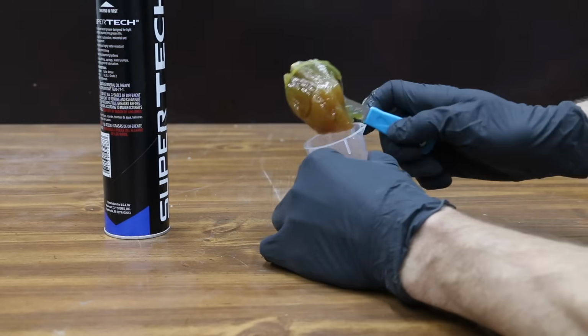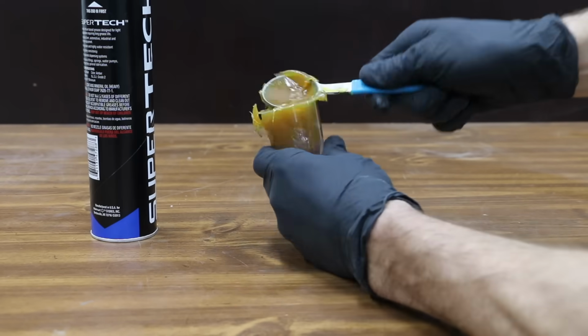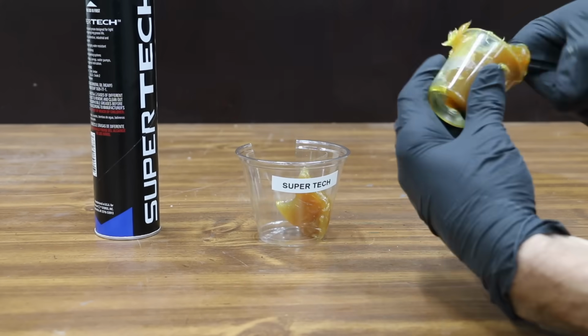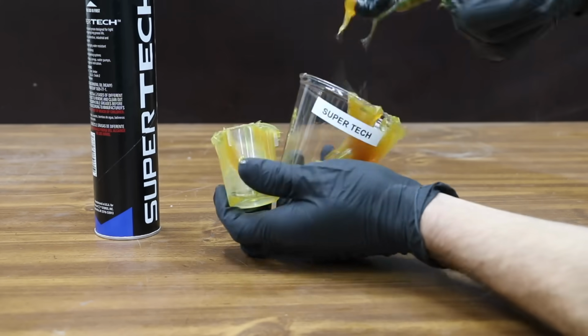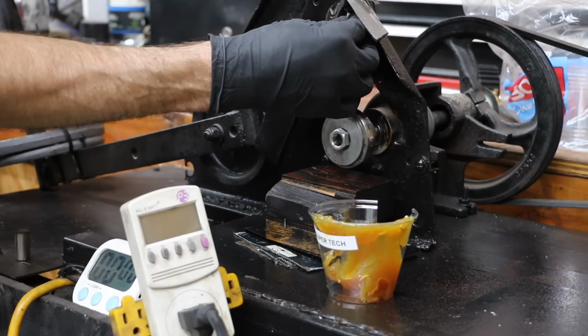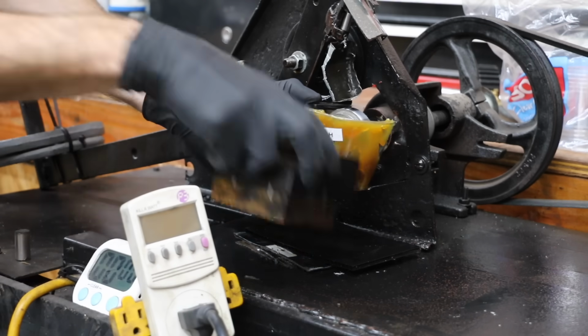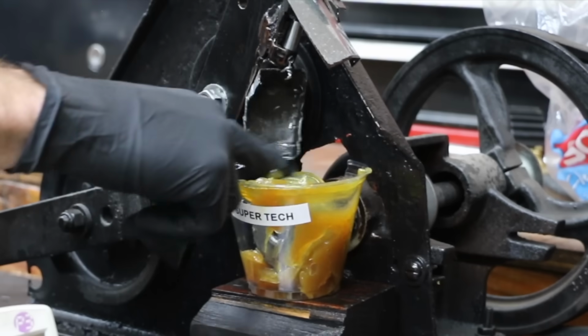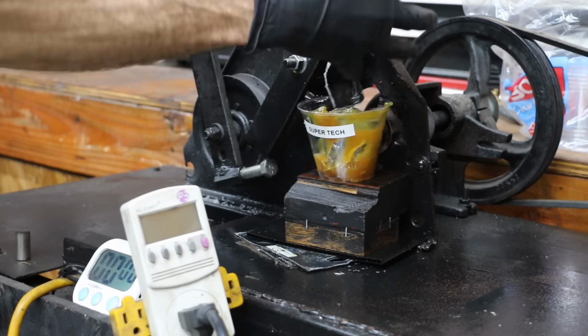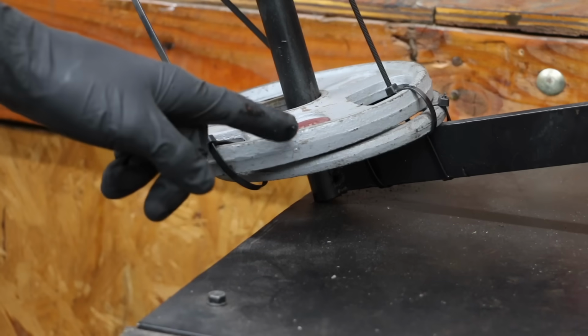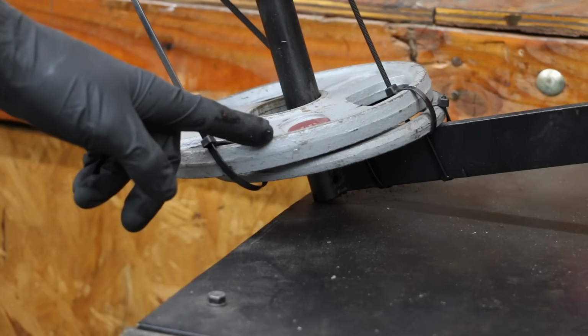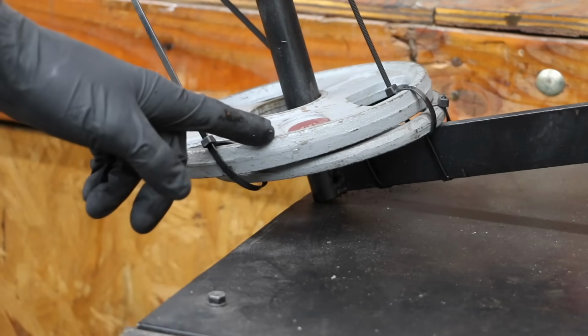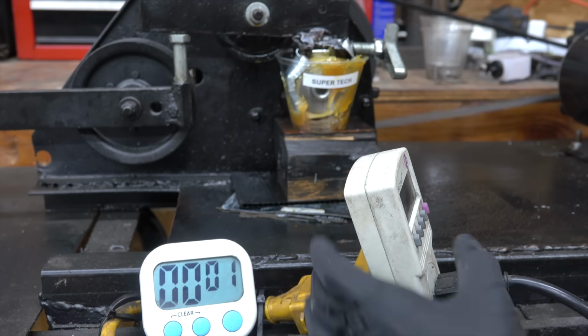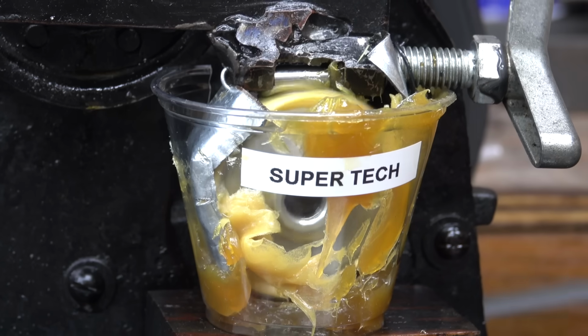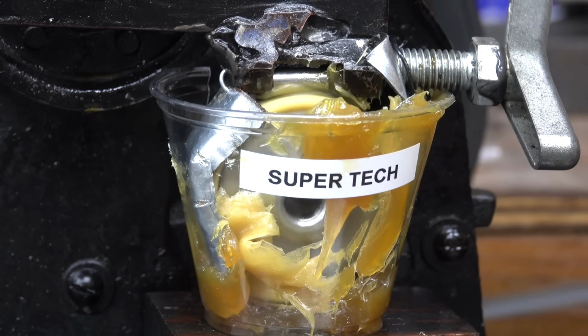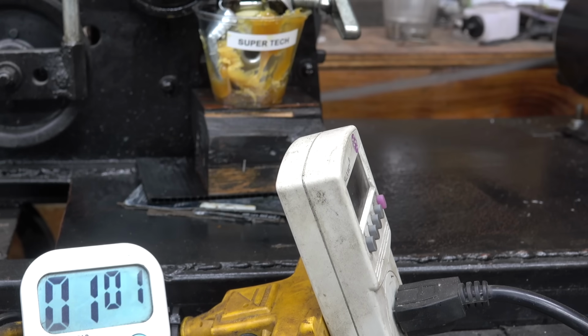In the next test, we'll be comparing the film strength of Supertech to Lucas using the lubricity tester. I'll begin by adding approximately 40 milliliters of grease into the test cup. I'll make sure that both the test bearing and the wheel have a thorough coat of grease on each surface before the test begins. Since grease is an extreme pressure lubricant, I've increased the amount of downward force applied to the bearing by 50%. The test will last right at 2 minutes. After the test, we'll compare the size of the wear scar on each bearing to see which product offers the best protection against wear.